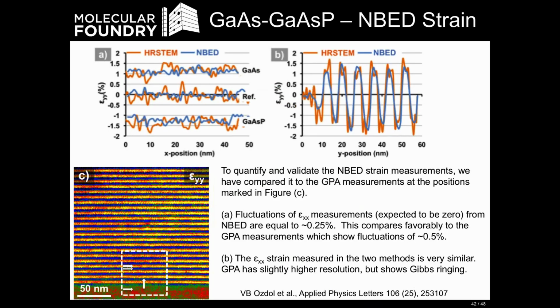And so if we compare the two, Barak's plot here in the upper left and upper right, you can see the comparison between the high resolution STEM atomic resolution GPA strain and the nanobeam electron diffraction 4D STEM experiment. And so perpendicular to the growth direction scan in A, you can see it's a noisy pattern, but overall the strain values are zero. And they do shift a little bit between the two different lattices. And if you go into the other direction, in this case, along the growth direction, the epsilon YY strain comparison in B between HR STEM, the conventional experiment, and our 4D NBED experiment, you can see they're in very, very good agreement.